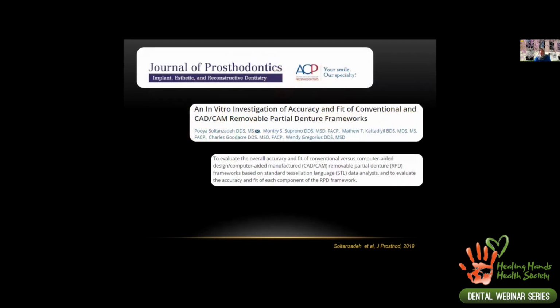So how are they fitting though? What's the accuracy on these? It's getting more accurate, I can tell you that. And a lot of the inaccuracy that happens from selective laser melting comes from how that metal is heat treated post-production, especially for the RPD frameworks, because our appliance is quite fragile in a way that everything has to fit at the same time in every component.